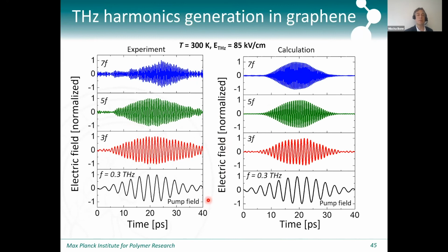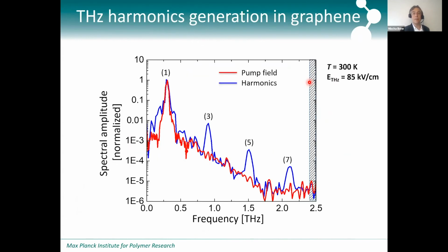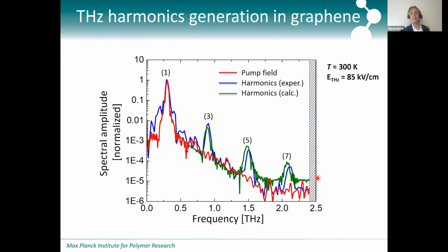I mean, there's a couple of details that we miss. So one of those details is that for the seventh harmonic, there's a clear delay between the maximum in the fundamental and in the seventh harmonic, which we don't see in the calculation. But I think by and large, given that we're not theorists, this is a very simple thermodynamic model. It works remarkably well. And that is also true if we calculate the spectrum with our model. We capture the relative intensities of the different harmonics fairly well, I would say.